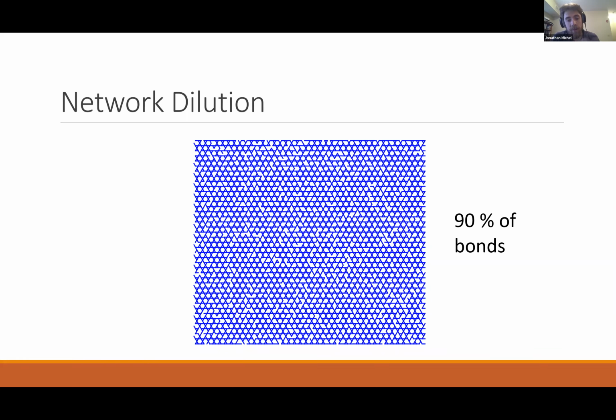We liken this process of varying the amount of material we retain in this model network to varying the concentration of collagen in the articular cartilage. So in our model, we take the collagen concentration to be in correspondence with the fraction of bonds that we retain in our network. In these images, I've pared away material in a completely random, spatially homogeneous fashion.